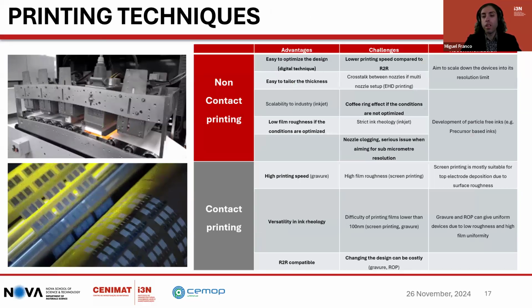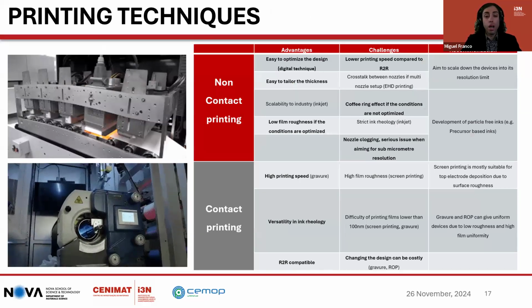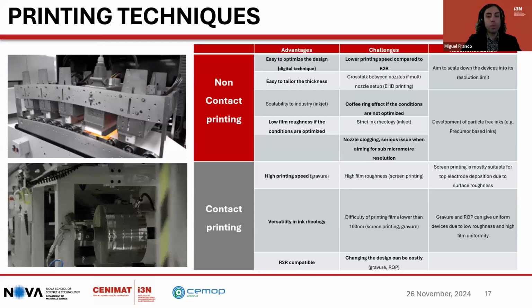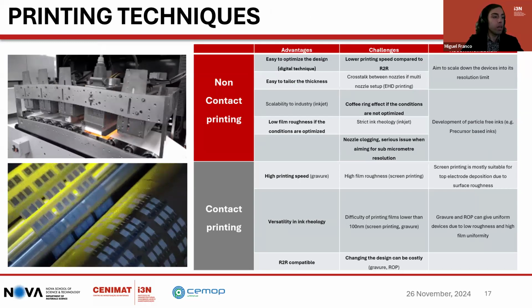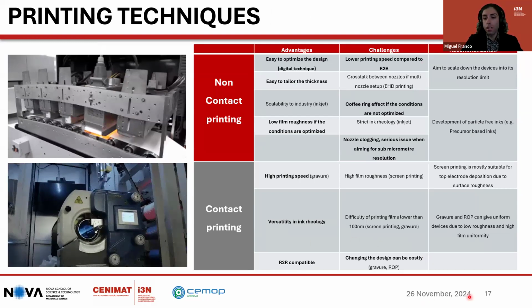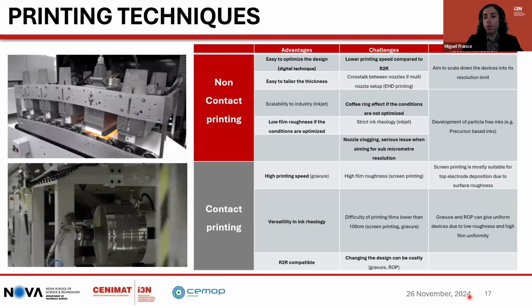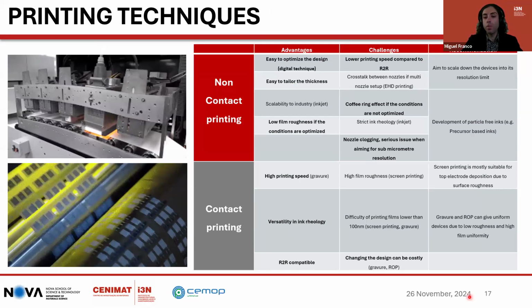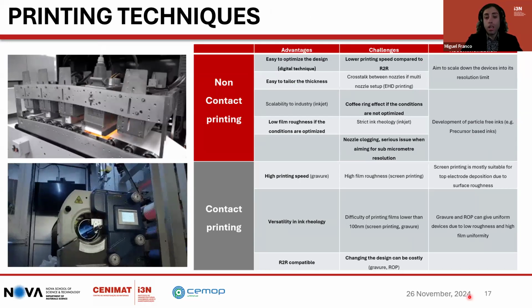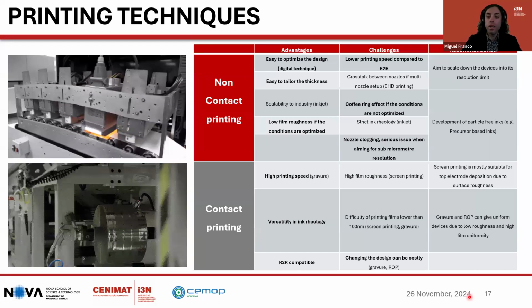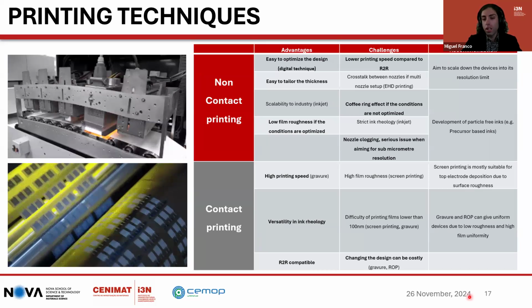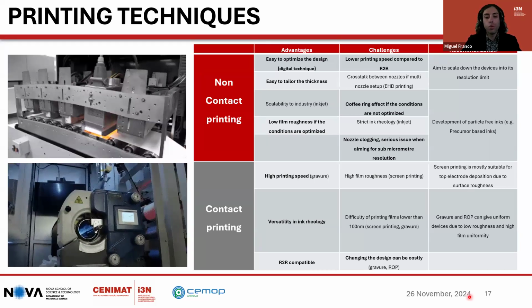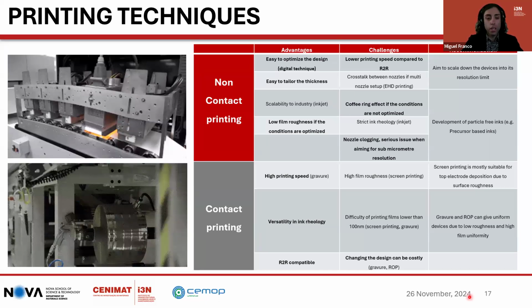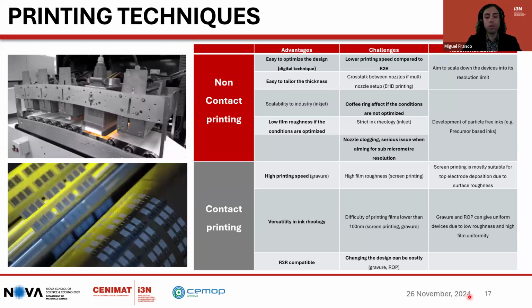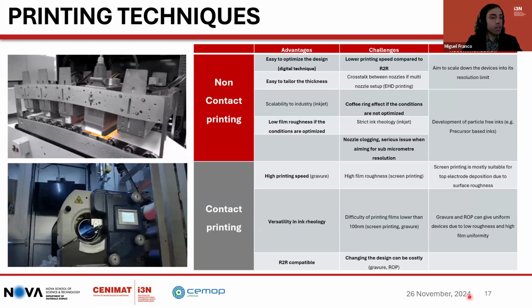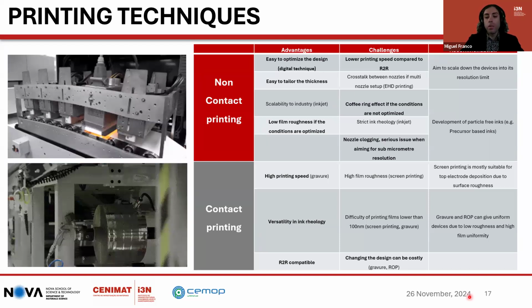Here is a summary of the advantages and challenges of contact and non-contact printing techniques. Contact printing techniques allow high-speed printing and are roll-to-roll compatible. However, changing the design requires the fabrication of new mask cylinders, which is a big drawback at research level and design optimization. Screen printing is a more affordable technique, but for thin film applications, it is limited by high surface roughness and difficulty achieving thickness lower than 1 micrometer. However, for sensors or to deposit thick films, it is an excellent and reliable printing deposition technique.